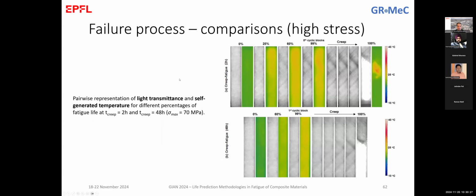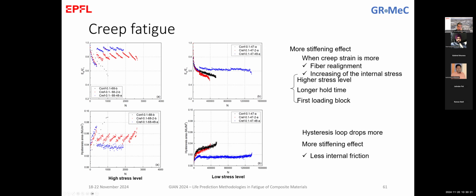So let me open everything here to discuss again. Stiffness degradation. You remember we expect a behavior with a monotonically decreasing trend, but here, because of the interruptions, we see that the material was recovering and then starting again to drop. The same for different. So this is for high stress levels. The same for lower stress levels. I'm discussing here, for example, the blue curve. We have a stiffness that drops, and then while we interrupt, the stiffness recovers and goes back, and so on until the failure. And the same behavior happens with the hysteresis loop areas.